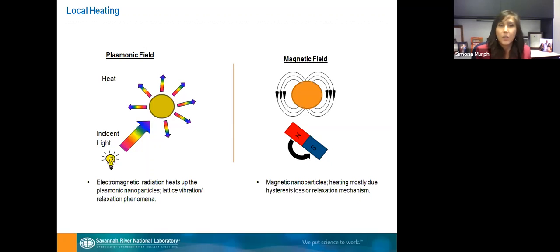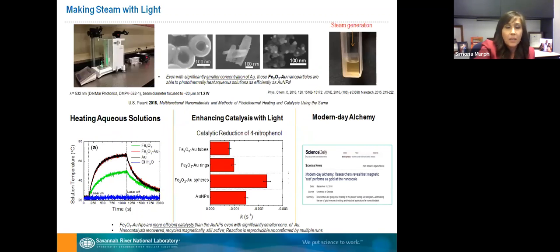If you are using light, you have different lattice vibration and relaxation phenomena, or when you're talking about magnetic nanoparticles, you are talking about the hysteresis loss or relaxation mechanism. So how did we implement this? We were making steam with light. We use a low laser light power, and we use these gold iron oxide hybrid nanostructures. And of course, we use different shapes. We have rings, we have tubes, and we have spheres. And these bright spots, they're the gold nanostructures.